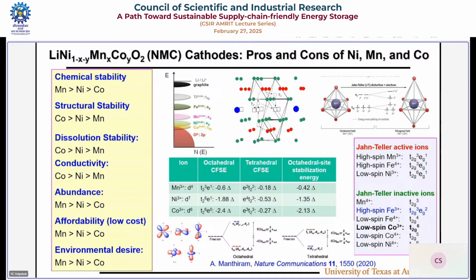And if I take this difference, you see, I get a quantity that tells me to what extent these ions prefer octahedral coordination versus tetrahedral coordination. You see here cobalt 3+, huge, large negative. That means it's much more stable in the octahedral site. So that guy loves the octahedral site. Cobalt hates the tetrahedral site. It doesn't want to move from that layer to this layer. So that I would call a gift. You hear me? That's a gift. That's why that was commercialized first.